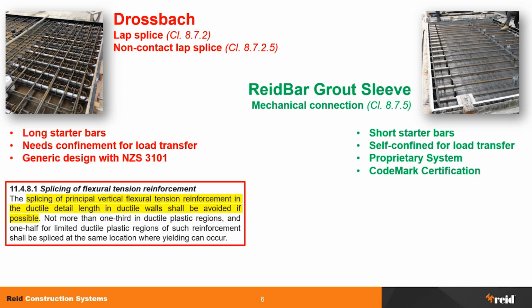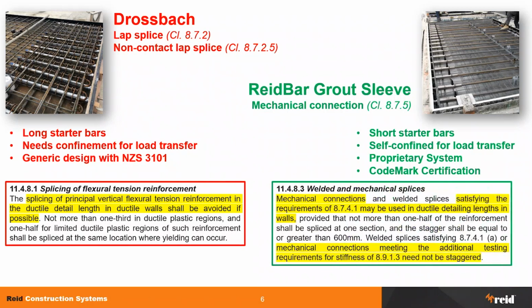For the Drossbach, if we look at 3101, when we have these kinds of connections, they shall be avoided if possible in ductile regions of the panels. And if it's not possible to avoid, they need to be staggered. For the grout sleeve, on the other hand, because it's tested as a mechanical splice, and in particular also tested to clause 8.9.1.3, which references ISO 15835, the low cycle fatigue test, and because it's tested against those requirements, it can be used also in a ductile region of a panel without the need for staggering.